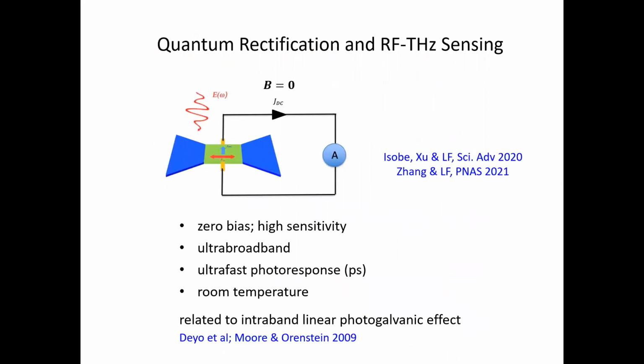In the last 5 minutes, let me briefly mention some future directions. So far I've shown you experiments detecting this nonlinear Hall effect at DC or at low frequency, but back to the original motivation, we believe it should work at much higher frequencies, in the RF and even in the terahertz range. In particular, this nonlinear Hall effect can convert an AC input signal into a DC output, and therefore it can be used as a photodetector, right? It works without any applied external bias, and it could be very sensitive. Also, because it doesn't involve any PN junctions, it's not limited by a cutoff frequency, so it could work in a very broad frequency range. Also, it may work at room temperature.